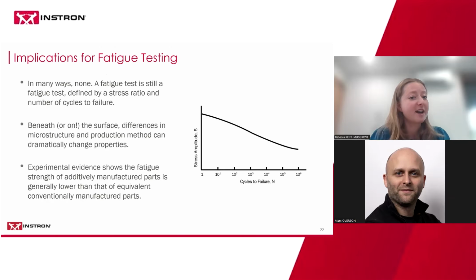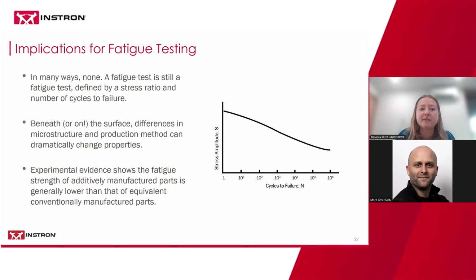However, beneath the surface, or often on the surface, the differences in microstructure and production method can dramatically change the properties. What we've seen is experimental evidence generally showing that the fatigue strength of additively manufactured parts is lower than that of their equivalent conventionally manufactured parts. It's not always the case, but it is the general case.